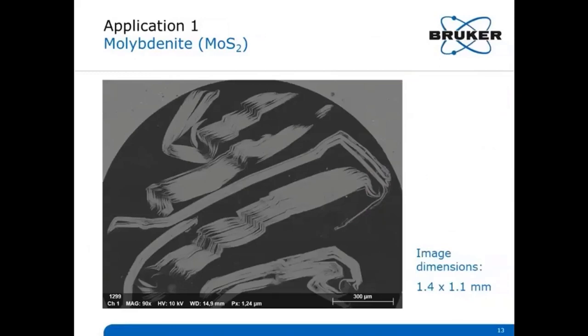Bulk molybdenum disulfide is a diamagnetic indirect bandgap semiconductor similar to silicon with a bandgap of 1.23 electron volts, while molybdenum disulfide monolayers have a direct 1.8 electron volts electronic bandgap supporting switchable transistors and photodetectors.